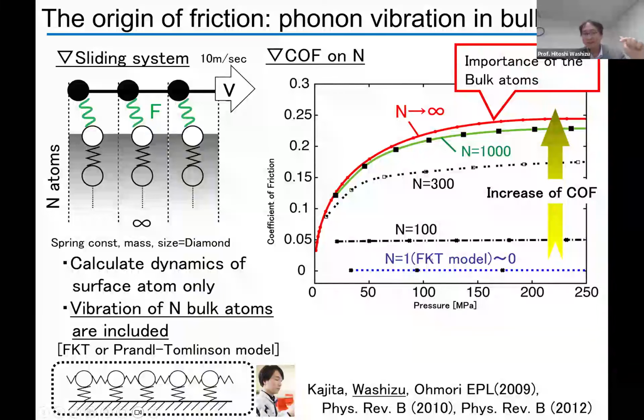If there's only one single atom, the coefficient of friction is very low. This is because the bond is very stiff and the bond parameter is high, so the atoms do not move, and energy dissipation cannot occur. But if we add some number of atoms in the deep bulk side, 100, 300, and 1000, these are obtained by simulation, okay? And this infinite value was calculated by Dr. Kajita, who was very young and made a very good theoretical effort. He calculated the infinite case, and the simulation value for 1000 and the infinite value are the same. All right. So this means that the origin of friction is phonon vibration in the bulk. And about 1000. Of course, this depends on the material, but for diamond, it's 1000.